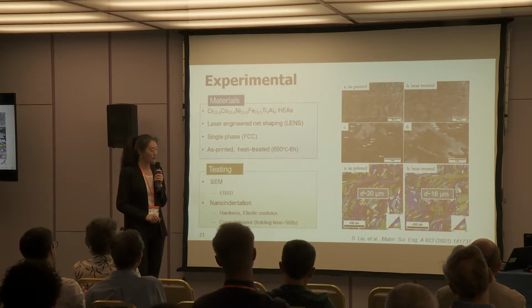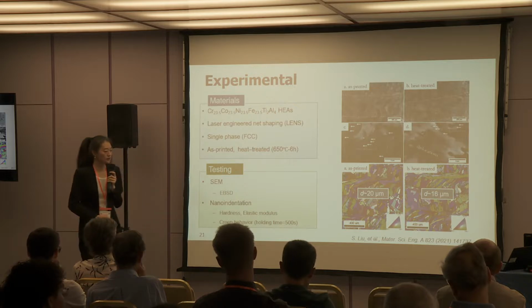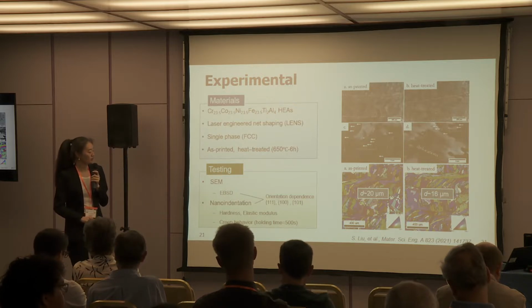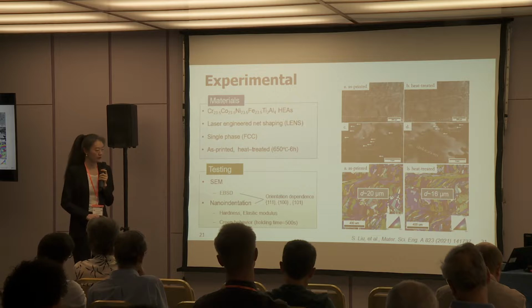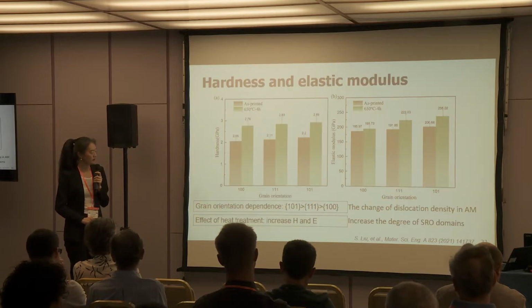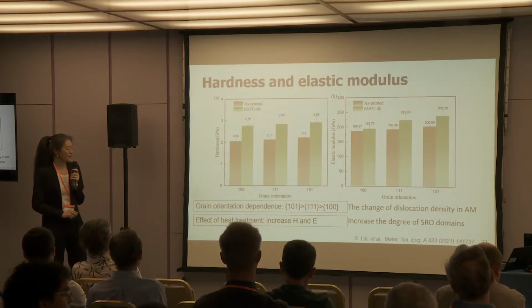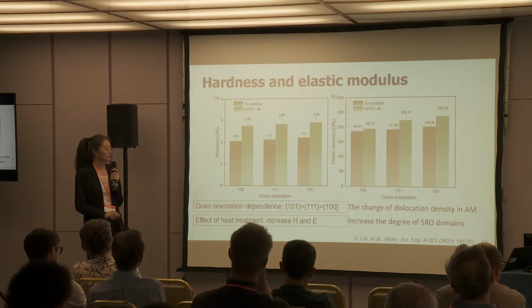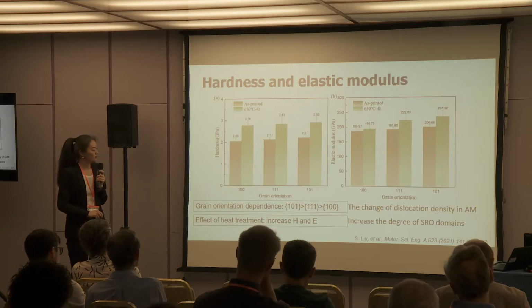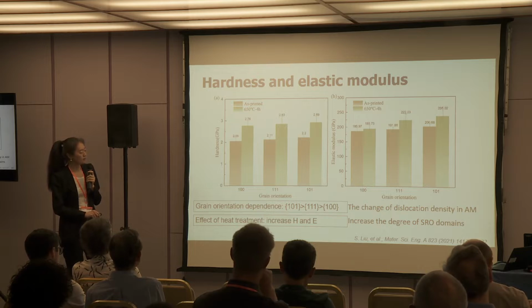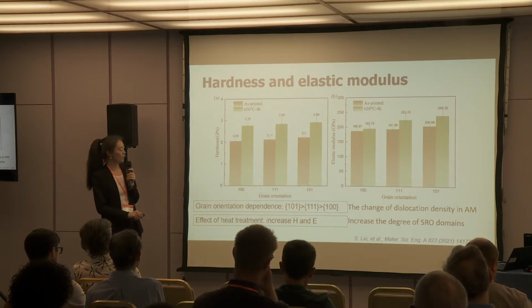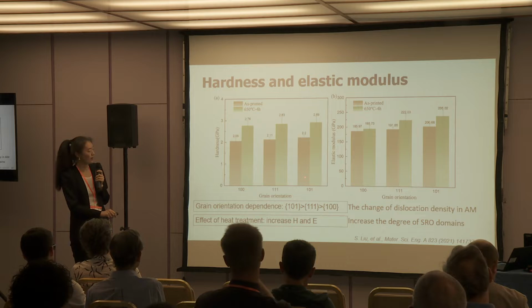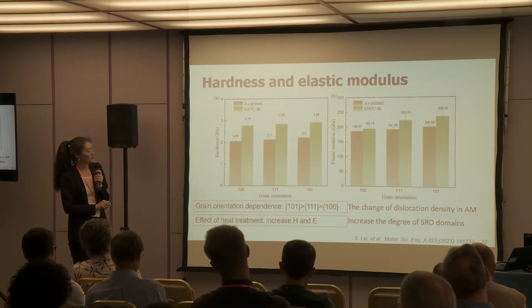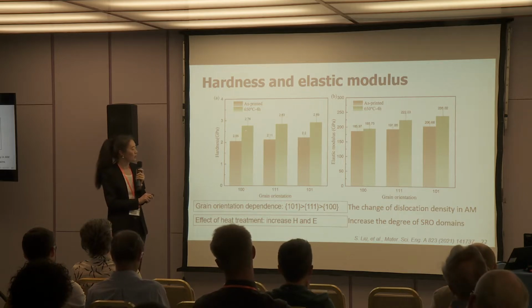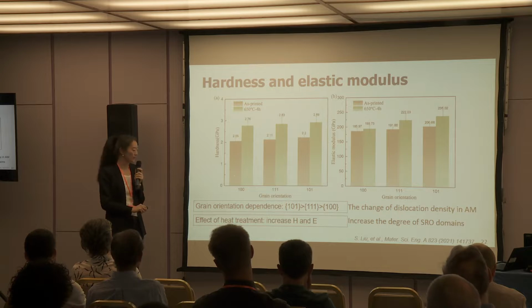With EBSD, we are able to identify different grain orientations. So we test mainly these 3 primary grain orientations, and then we see the results. Left is the hardness, right is the elastic modulus. We can see that both hardness and elastic modulus follow the same order, where the 101 orientation has the highest value. And the heat-treated material also has a higher value compared to as-printed.